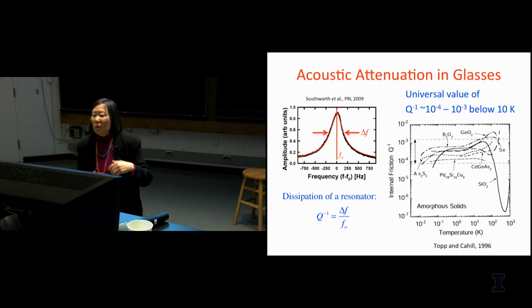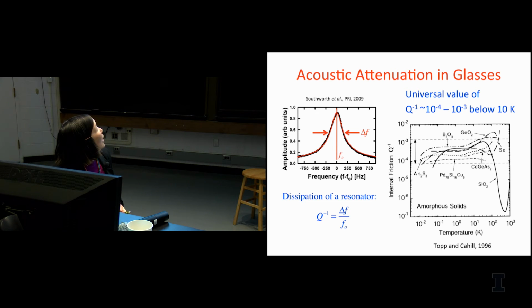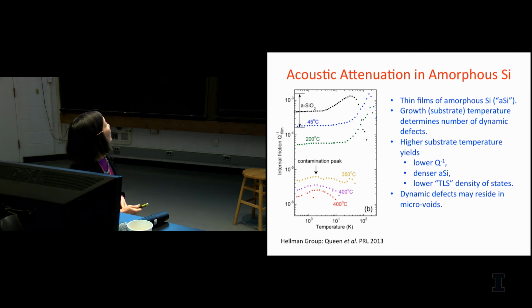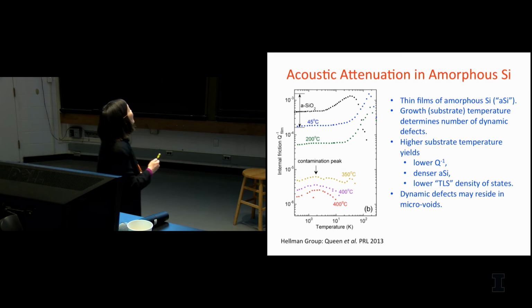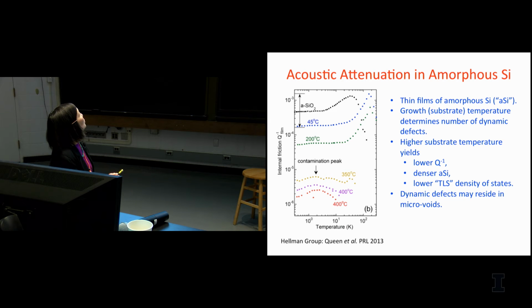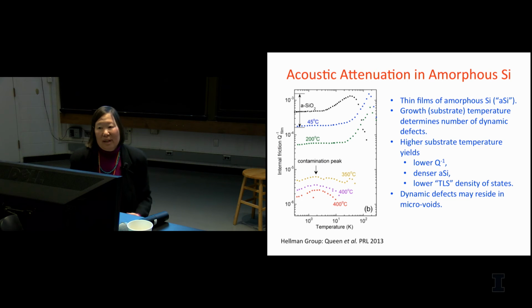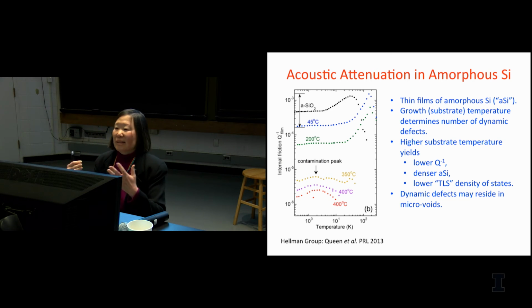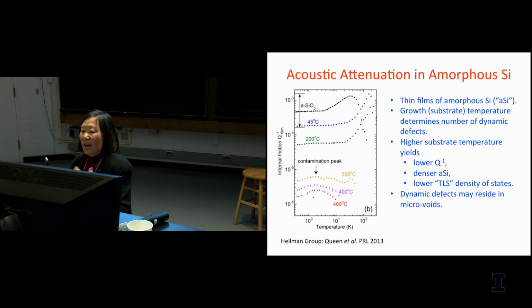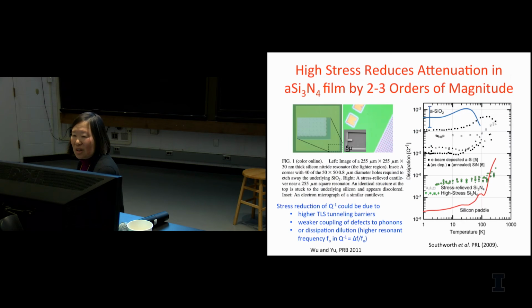So there's also evidence from the Q inverse, this internal friction, and the Hellman group with these thin films of silicon. Here's internal friction versus temperature in a log-log plot. This region here is where glasses reside. If you grow it at a higher temperature, you see a reduction in this internal friction. And again, you have the idea that you've made the film denser and left less room for these non-phononic degrees of freedom, as Tony likes to call them.